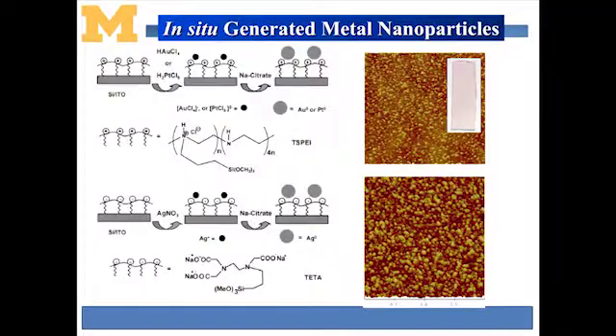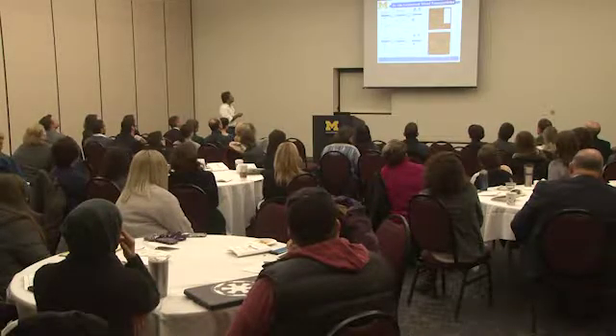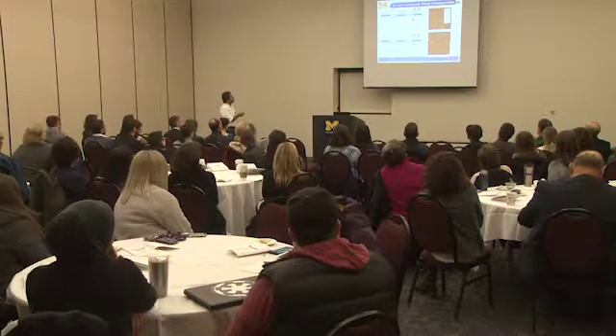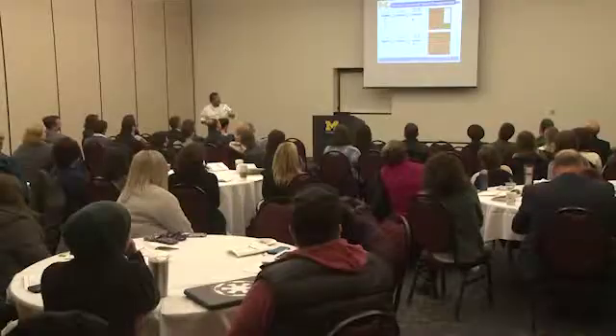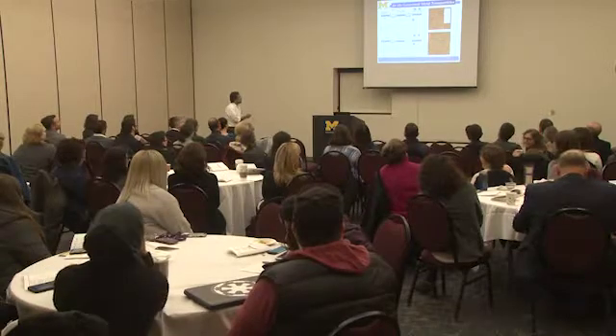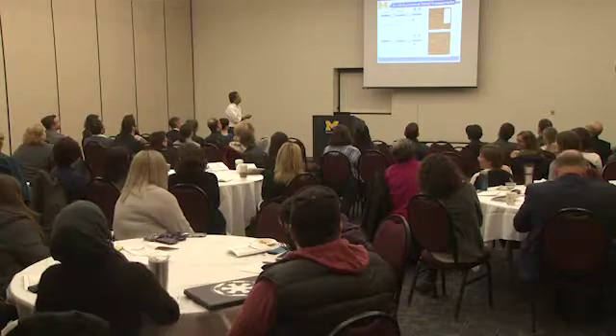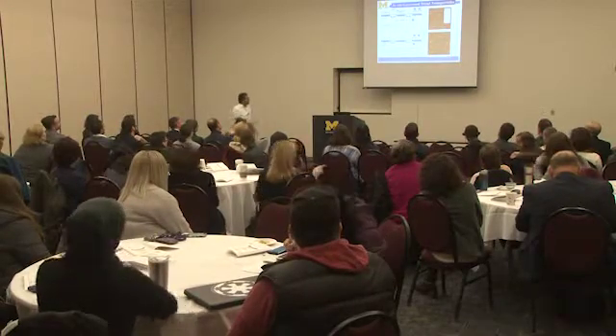Going forward, we are going to use two-dimensional nanoparticle assemblies for nanocatalysis, generate things on a spherical surface for cancer remediation as a heat absorber, and look at the biosensor. We take a surface, functionalize it with a positive charge layer, hook up an ion, and then exchange that ion to a specific nanoparticle. Using atomic force microscopy, you can see at the nanoscale. We generate gold nanoparticles and you can see a surface becoming red in color. Here is a silver nanoparticle.